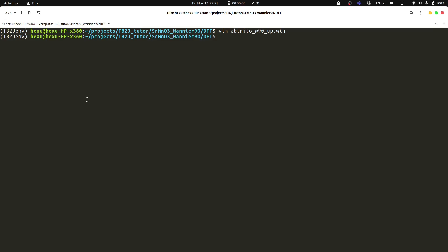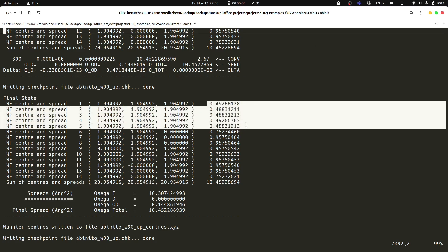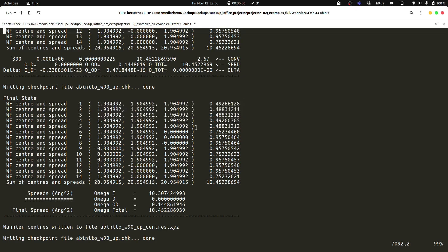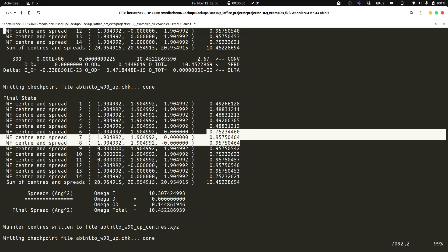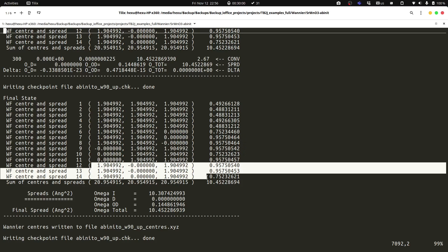And then we can run abinit to generate the initial projectors. And then we can run wannier90 to get the files we need. Note that after we run wannier90, we need to check the Wannier center and the spread to see if the Wannier functions are well localized. And they are localized near the atoms. So here we can see that we have 5 Wannier functions which are very localized. And they are close to the same atom, which is manganese. And we could see these three are close to one of the oxygen, and these three as well, and these three as well. So we could see that in this calculation, the Wannier functions are well localized.